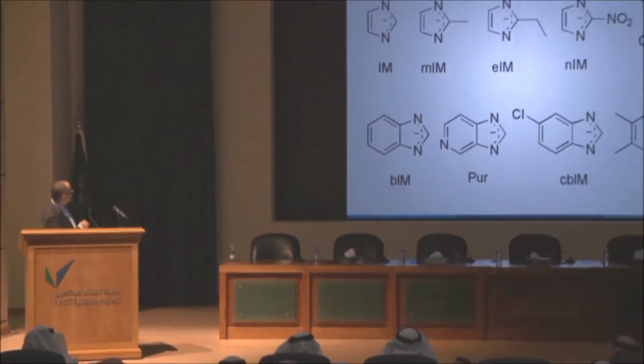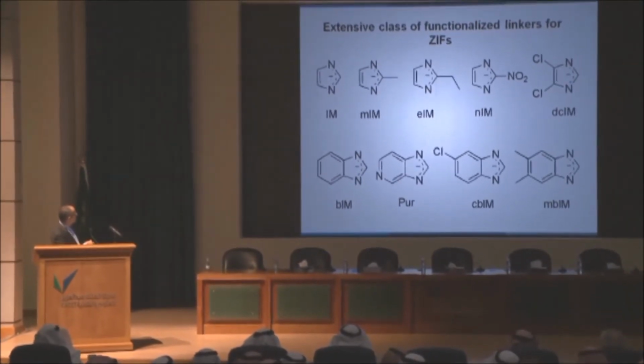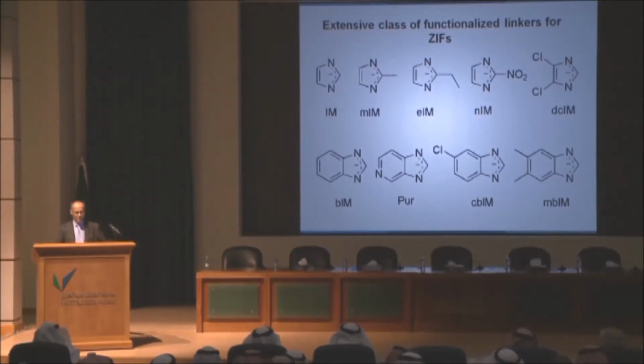And now with just this idea, it took us about 4 years to make this work, but once you make it work, it works for everything. So this is one of the structures of ZIFs. It's known here as a sodalite, and in this case, you see it as one of the cages as a ZIF. So not only can you link this entity, but also any entity, functionalized or otherwise, can be linked as long as you have those two nitrogens in the position that I mentioned before, as you can see here.